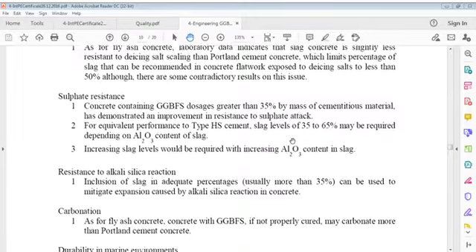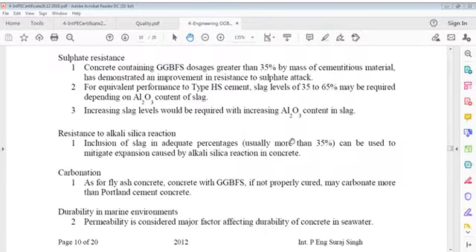Sulfate resistance. Concrete containing GGBS dosages greater than 35% by mass of cementitious material has demonstrated an improvement in resistance to sulfate attack. For equivalent performance to type HS cement, slag levels of 35 to 65% may be required depending on the Al2O3 content of the slag. Increasing slag levels would be required with increasing Al2O3 content in slag.